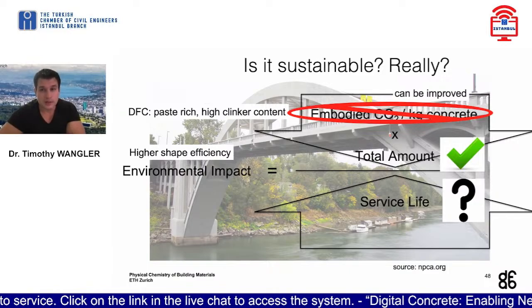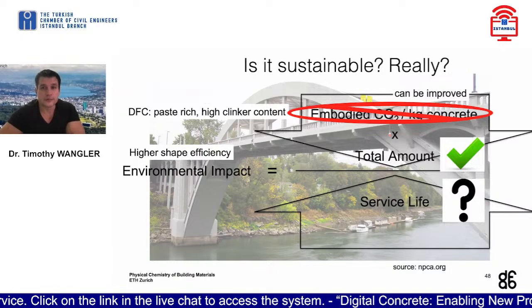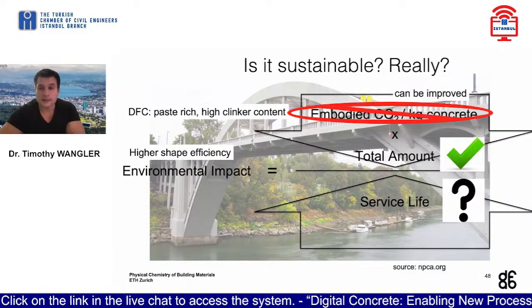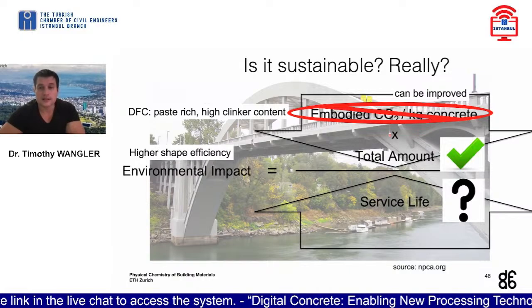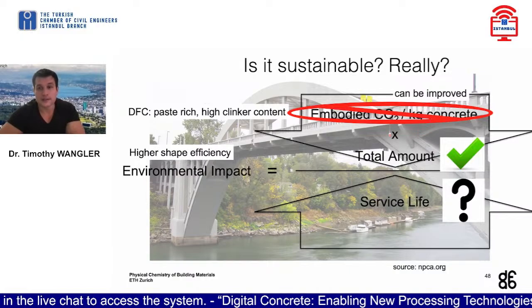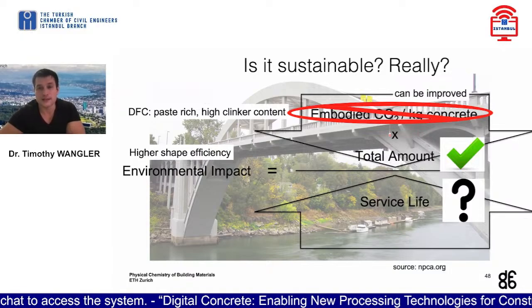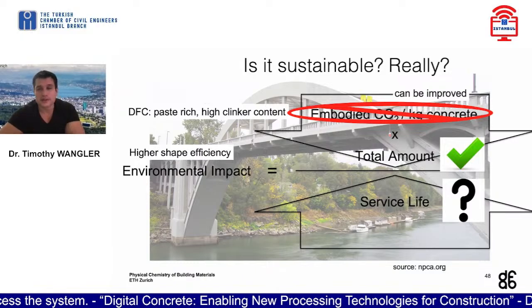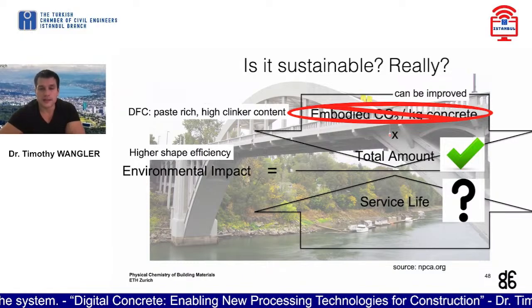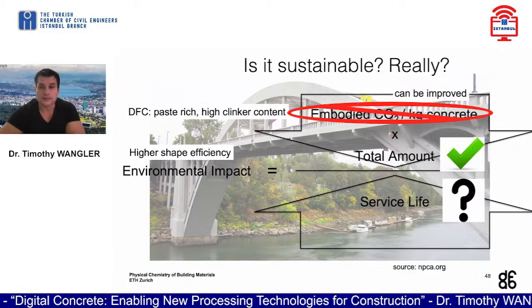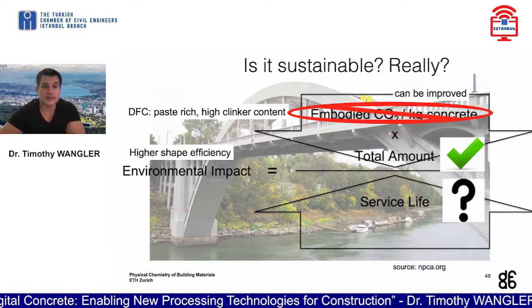But we still have the question of service life. So that's something that still needs a lot of research. The research has already started on it, and actually with all these layer interfaces, you could call them cold joints sometimes in 3D printed concretes. They can become cold joints when you wait too long between layers. Then we can have potentially serious problems with respect to durability. So this is still an open question and it's still being evaluated.